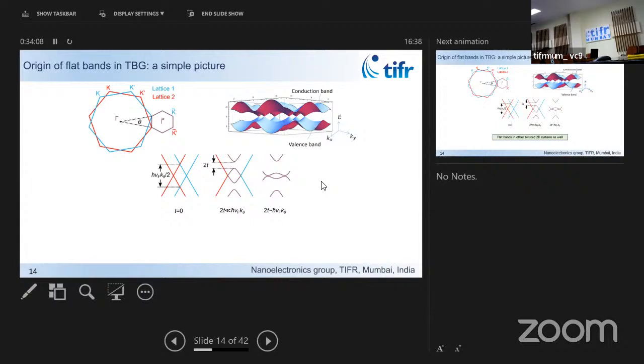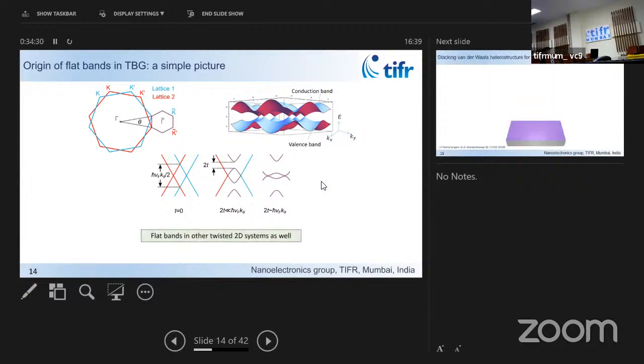And the moiré zone will actually have regions which are electronic states that are flat, which don't have much spread. Just to give you an idea, this spread is roughly a few meV to about 10 meV. It's controllable in systems with angle or some other knob. Okay, so these flat bands.